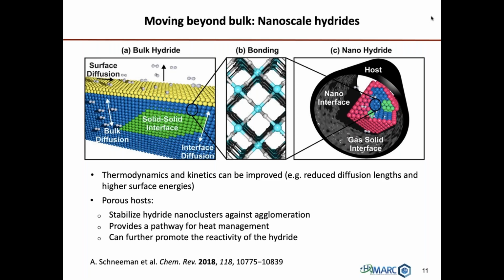And bulk metal hydrides, at least on paper, have the highest capacity, but one of the things that limits them often is their thermodynamics, as well as the rate at which they release hydrogen. It's been learned through a lot of research that HyMARC has done, but also others, that if you scale down the critical dimension of a metal hydride to something like a few nanometers, and this is a little bit of a vague area, it could be a few nanometers up to 10, 20, it's not really been nailed down that clearly. But if you do that, there's tons of evidence that shows that you will destabilize the material and it will release its hydrogen at lower temperature.